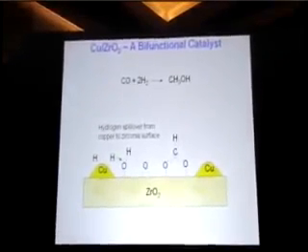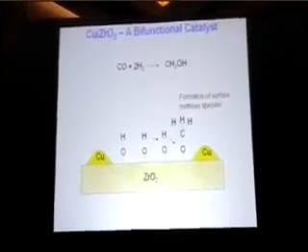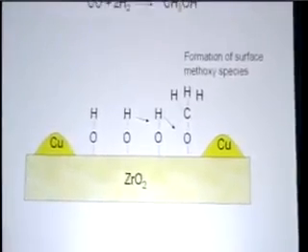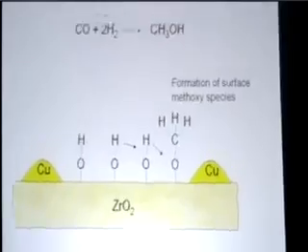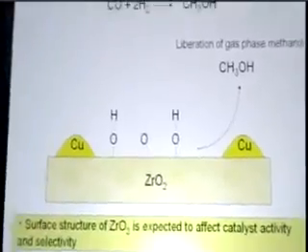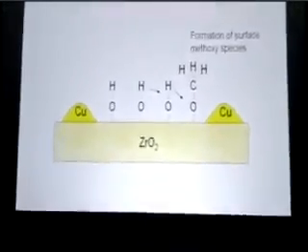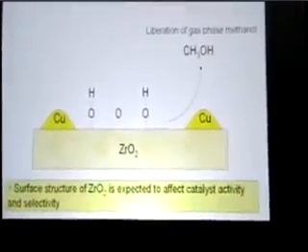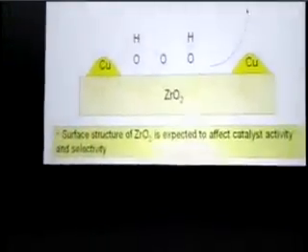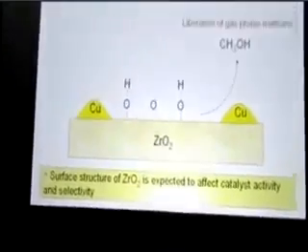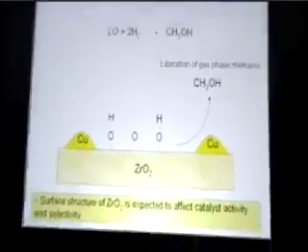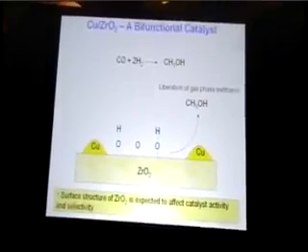That's shown here. We're spilling over the hydrogen, and it gets up to the formate and hydrogenates it to the methoxide group, which you can see spectroscopically by infrared, and you can see the dynamics of that process. That's relatively fast. And what is slow is the removal of this methoxide to make methanol. In fact, if we follow the dynamics of methoxide and we follow the dynamics in the gas phase of the methanol, they're 1-to-1. So the time constants for these two processes are related, and therefore that methoxide is in fact the precursor to methanol.